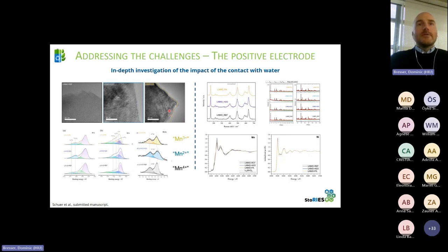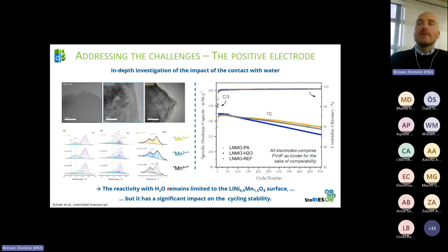But with more surface sensitive techniques like high resolution transmission electron microscopy or XPS, what we've seen in the case of water and in the case of phosphoric acid is the formation of a very thin amorphous layer on top of the material, less than a nanometer. And we observe a reduction of manganese from 4+ in the reference to 2+ in contact with water and 3+ in contact with phosphoric acid. To be fair, the reactivity remains limited to the surface area apparently.